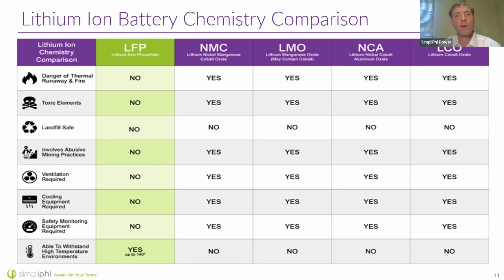The reason the other cobalt-based chemistries exist is because you're trying to make vehicles very light. And so typically to have light batteries with high energy densities, they're using cobalt. One of the problems with cobalt, and so I'll run through the chart here, is the danger of thermal runaway. I'll get into what that means, but basically it's a chain reaction where one cell can get hot, catch fire, and catch other cells on fire. Lithium iron phosphate has the least likelihood of going into thermal runaway. You really have to push lithium iron phosphate in order to get it to catch fire.